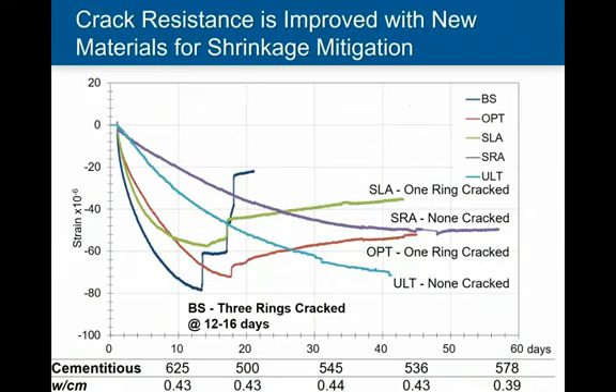And so here are the results of ring tests. For new construction, we're seeing the BS curve on the very far left side. That's bridge structure. That's a standard IDOT mixture. And this is a concrete that is prescriptive and is used quite frequently in the industry. And as we move towards the right, the green, the red, the lighter blue, and the purple curves, these are the various shrinkage mitigation strategies that were employed. And we saw, in some cases, outstanding performance in the long run, well past 28 days before any cracks were observed in the cases where shrinkage-reducing admixtures were used. And even in cases where just the saturated lightweight aggregate was employed, we saw outstanding cracking resistance, and in the case of optimization as well.